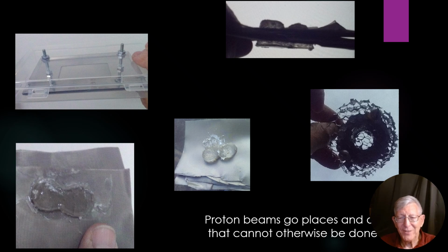Now, the one that's just to the left of my head is a different animal. This is a different experiment. What we did here, we wanted to demonstrate several possibilities all in one experiment. What you have here is two pieces of aluminum honeycomb that looks a little hexagonal design in aluminum. Aluminum honeycomb is, of course, used in many places where you need something that has certain rigidity but not a lot of weight. And we put that in a container, and we fill the container, flooding the honeycomb with a slurry of aluminum magnesium alloy slurried into the resin. And so the whole thing was filled up with this resin, and then we exposed it to a proton beam while it was rotating. And that's how we managed to make something that looks like a donut.